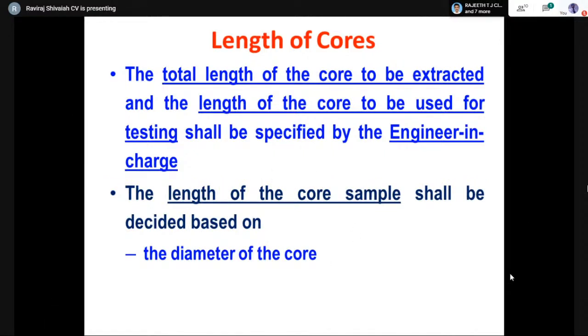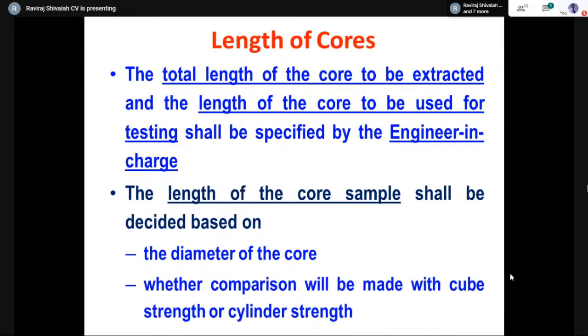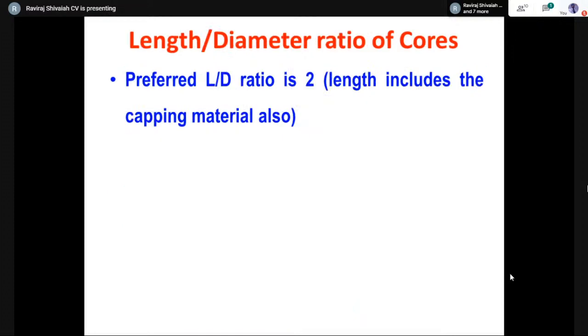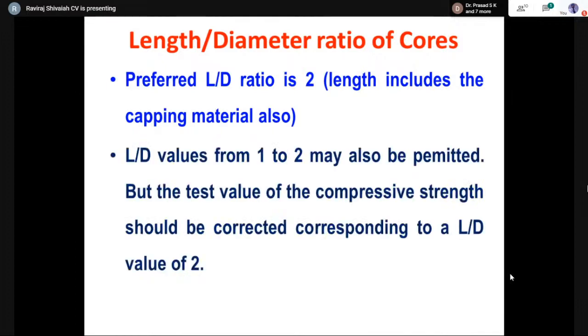And generally, we try to also see that the length of the core sample is related to the core diameter. If you take any standard testing, we have the length to diameter ratio being 2. So when you do an extraction, you can have something like 2.5, 2.2 or 2.3, then you can trim it to have an L by D ratio of 2 and then take it. Sometimes it may not be possible to have an L by D ratio of 2.